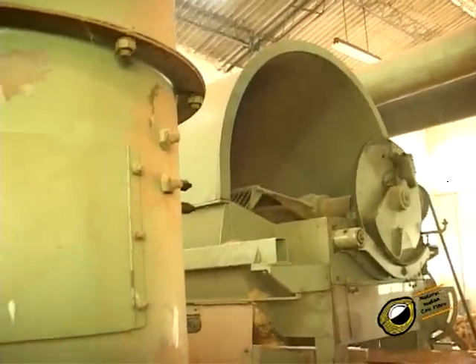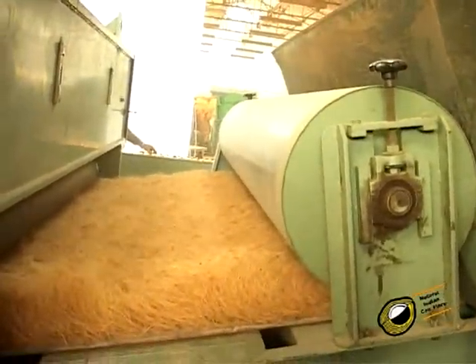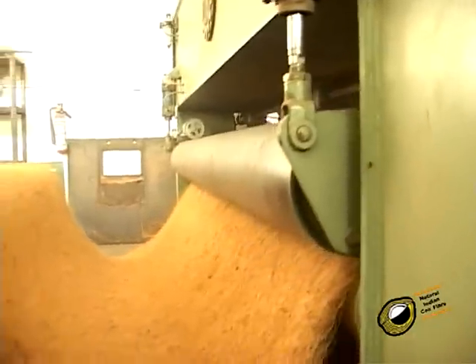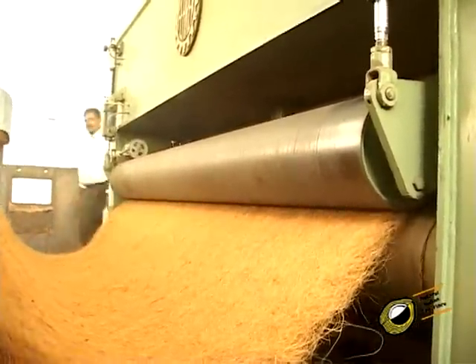The fiber pushed by the pusher comes between the rollers and is needle punched by a needle punching machine consisting of a reciprocating needle board, stripper plates, and base plates. The needles, having barbs, push some of the fibers vertically downward. The fibers form loops below the web bottom surface, by which the fibers are mechanically entangled to form a continuous length of sheet that can be handled easily.